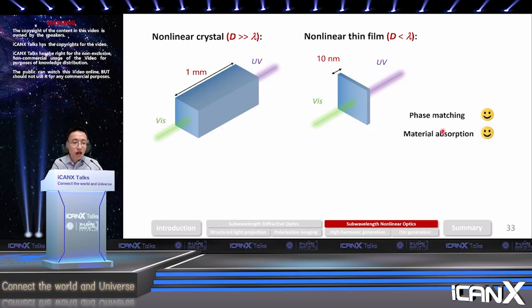Since if the thickness of the material is thinner than the coherence length for this harmonic generation, then we don't need to worry about phase matching anymore. And also, if the thickness is smaller than the absorption length of the material at this harmonic wavelength, then this material absorption also becomes less of an issue.